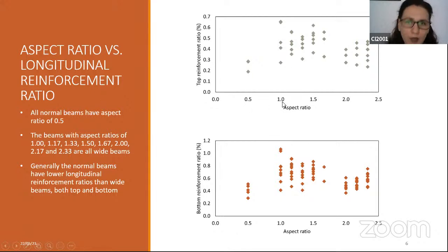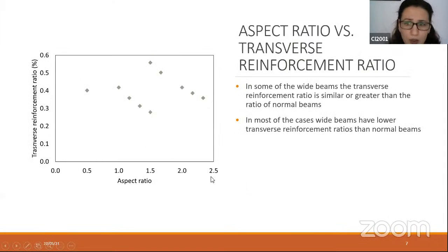And if we observe the relationship of aspect ratio with the top and bottom longitudinal reinforcement for the beams, we see that generally normal beams, the ones with the aspect ratio of 0.5, have lower reinforcement ratios, while wide beams have higher reinforcement ratios. This is something that we already expected. This is not a conclusion of our study, but it is just an observation. When it comes to the transverse reinforcement ratios, in some cases, wide beams had same or greater transverse reinforcement ratio than the normal beams, and in some cases they had a lower transverse reinforcement ratio.